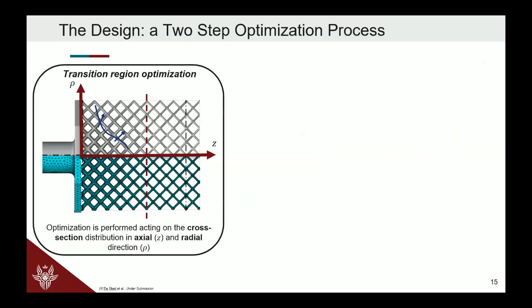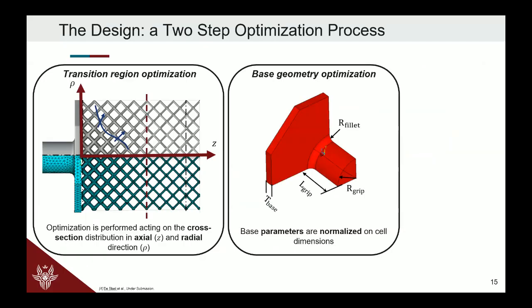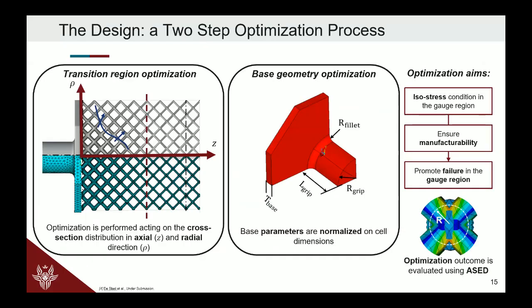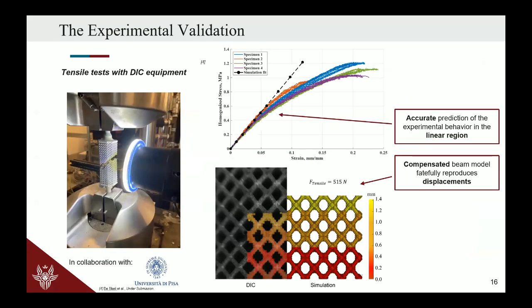So we designed new specimens with a kind of density that was varying along the length of the specimen itself. We studied numerically the problem to optimize this kind of specimen. And after that, we went through the experimental setup with the DIC to check if our predictions were correct and